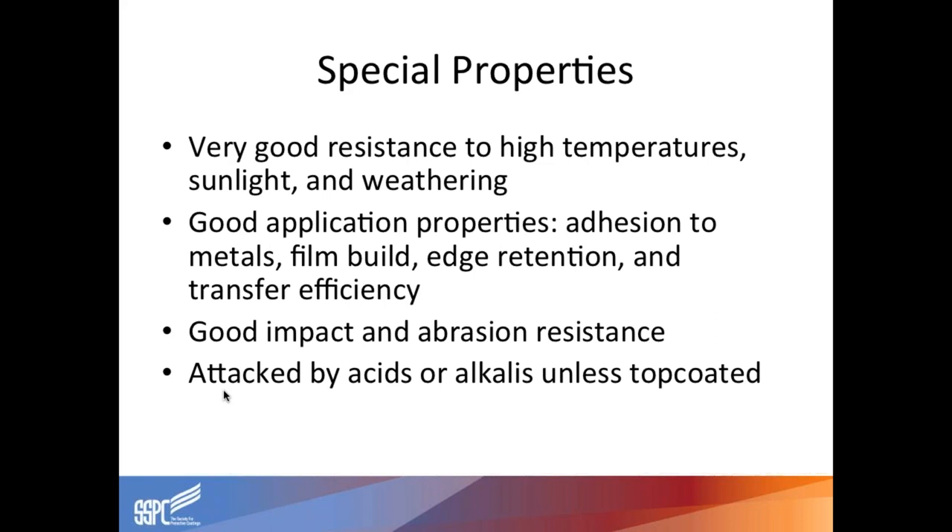Special properties: most of the materials have really high resistance to high temperatures. Aluminum is typically used upwards of 1,000 degrees, sometimes even 1,100 degree operating temps. Zinc has a lower melting point, so it's resistant up to about 500 degrees, and zinc-aluminum operates at 500 or less. The materials have really good bond values when the surface is prepped correctly. You can apply it as light as half a mil and continue to build up to whatever the desired thickness is. The thickness applied is relative to the service life — the more you put on, the longer the coating will last.